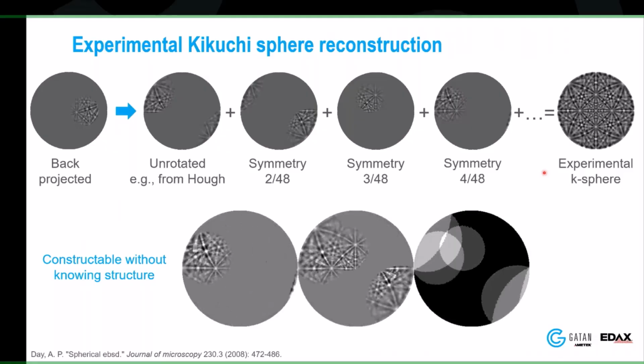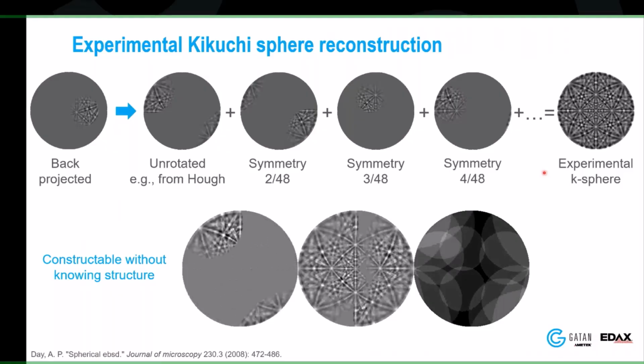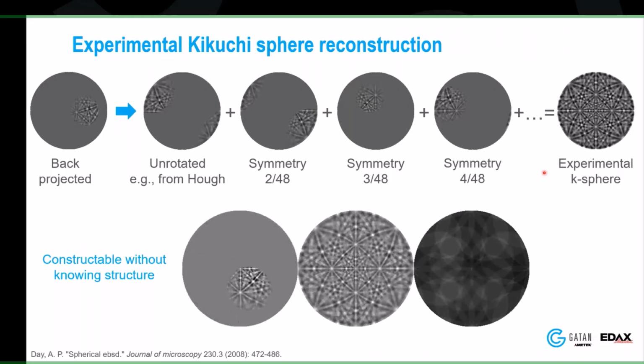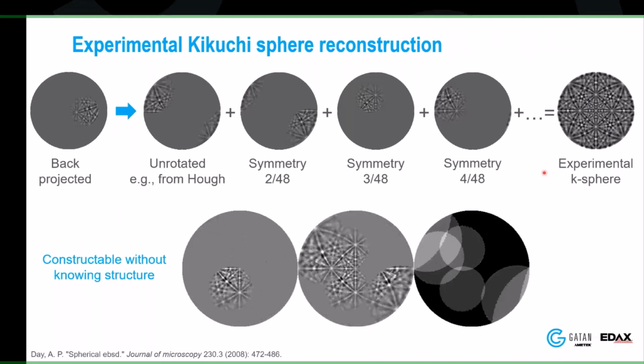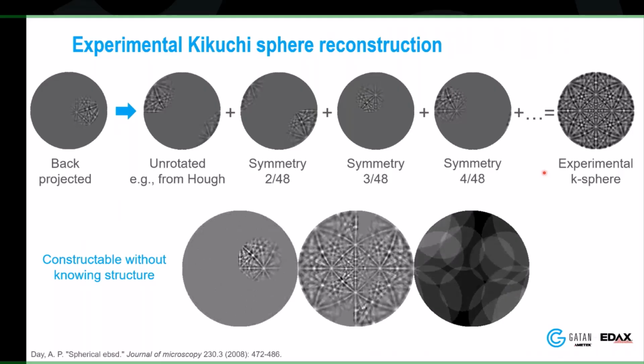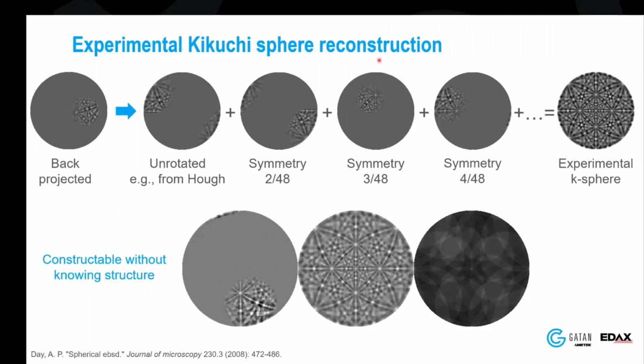So what we've done is take some work by Dr. Day and incorporated it in some ways into our software, basically saying, hey, I have patterns. Can I reconstruct the master pattern without even doing the dynamical simulations? If I do that, I'm basically making a master pattern that matches all my experimental conditions. So my geometry is all set, my intensity, all these kinds of things, and in the end I'm going to be comparing my experiment to my experiment. Because of that, I'm getting around some of the deviations that may exist in the dynamical simulation. This is what we call experimental Kikuchi sphere reconstruction.